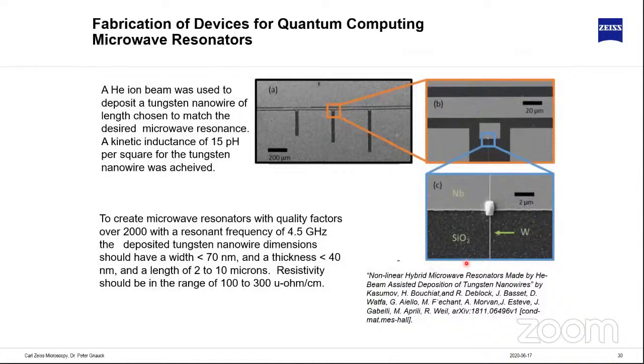And one application would be to go for quantum computing devices. So if we want to create a microwave resonator here, we would need a thin antenna which has a certain dimension, so width of 70 nanometers, thickness below 40 nanometers, and a length in the range of 2 to 10 microns. This can easily be achieved with depositing such materials with a helium beam. So because we can deposit relatively pure materials, we do not implant any heavy metals into them, and they work in a very nice way.